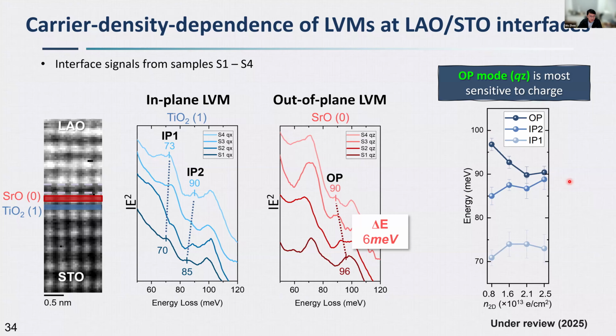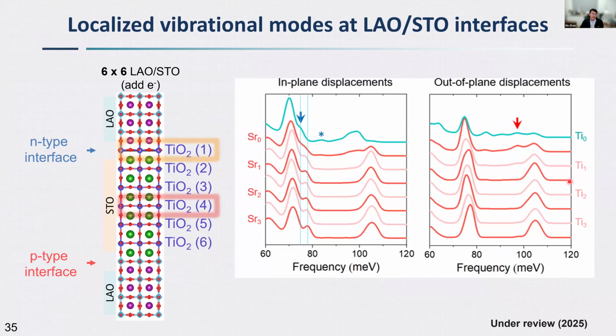And those are the experimental observations, and they are actually reproduced by our DFT calculations, which show these 2 additional in-plane vibrational modes and the additional out-of-plane vibrational modes. And you can see that those modes just fade away in the theory. It's just like 2 unit cells away from the interface. And in our experiment, it's about 4 unit cells.